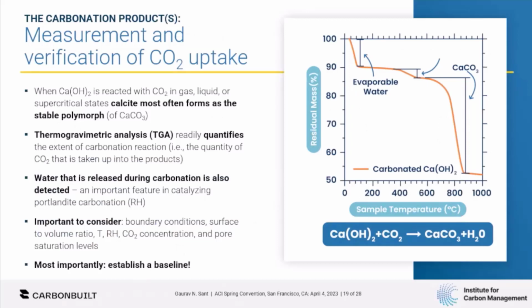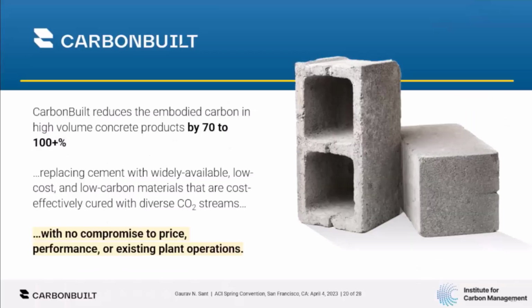It also allows for a really solid basis of measurement and verification. You can start to exactly measure how much CO2 you've taken up. Standard thermal analysis allows you to do this by having strong baselines of what your materials look like before you started carbonating, and what your materials look like after you carbonated them. You can start to get really strong complete mass balances around how much CO2 utilization you get.